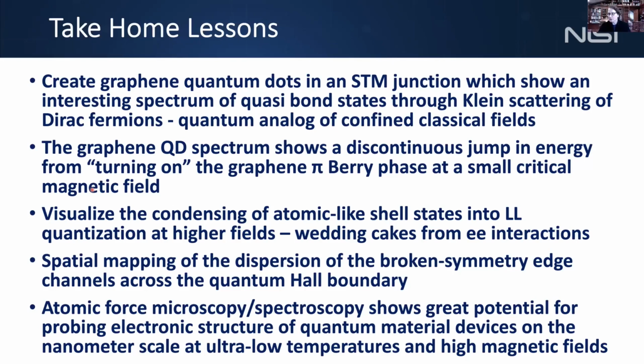We've created multiple quantum dots this way, which Daniel and Fresh have been working on. I showed you that at high magnetic fields, these shell states transition into Landau levels, starting first in the center and then moving out. And then you get compressible rings and disks. Those compressible regions themselves are Coulomb islands and can undergo single electron charging. So your tunnel probe and your gate become a top and bottom gate where you can do quantum dot charging physics. Then I showed you that we developed a new instrument that combines STM, AFM, and transport measurements